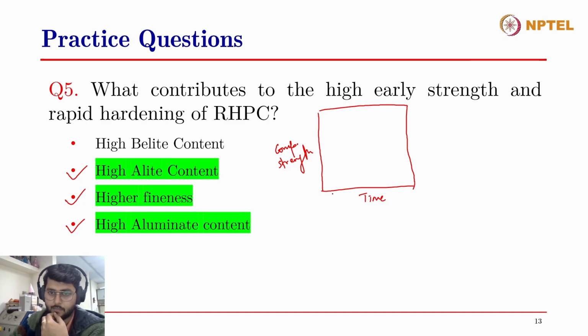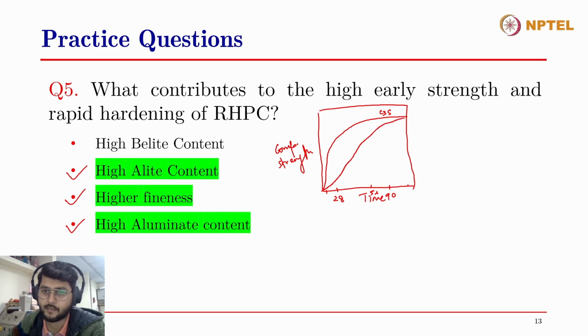And this is time, let's say in a log scale, and this is 28 days, and this is 56, 90, and so on. You would be able to see that in the pure Bogue phases, as in A-lite, the strength development goes like this. So this is C3S. In the case of B-lite, the strength development goes a little slower initially, but it catches up with A-lite at the end. So this is B-lite. But in the case of aluminates or ferrites, the strength development is limited to like this.